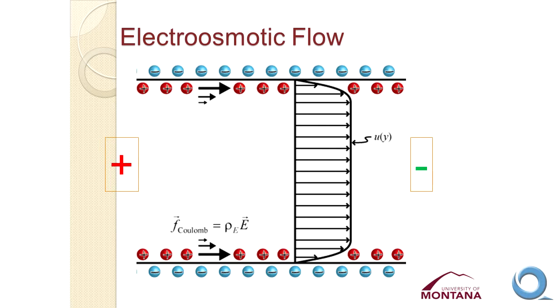And when we apply the potential, those cations migrate along the capillary and they draw the solution through the capillary with them. And this type of flow is characterized by a flat flow profile, which means that all compounds inside this capillary will move at the same velocity from the anodic end toward the cathodic end of the capillary. So that's a flow mechanism.